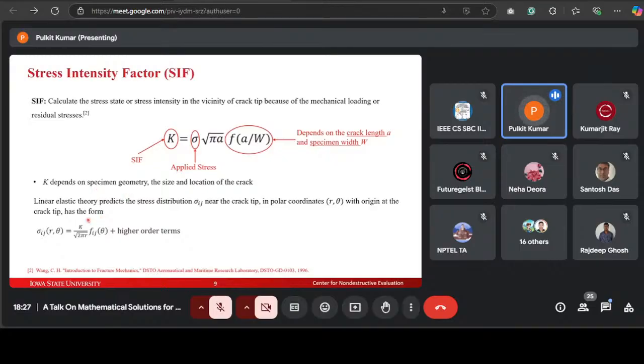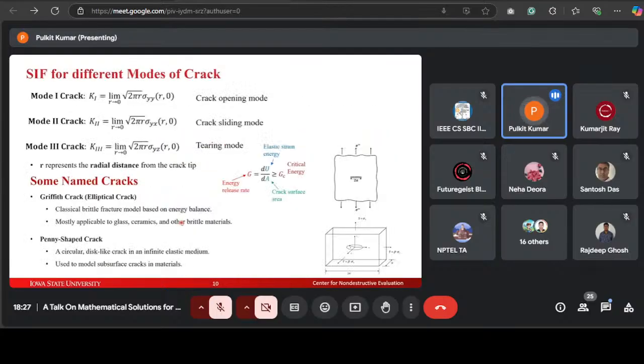The linear elastic theory predicts the stress distribution sigma ij near the crack tip in polar coordinates r, theta, with origin at the crack tip, has the form of this. It is theoretically constructed usually for homogeneous linear elastic material and is useful for providing a failure criterion for brittle materials. The stress intensity factors for the three modes of crack are denoted by K1, K2, and K3. And the term sigma YY represents the normal stress ahead of the crack along the crack plane.